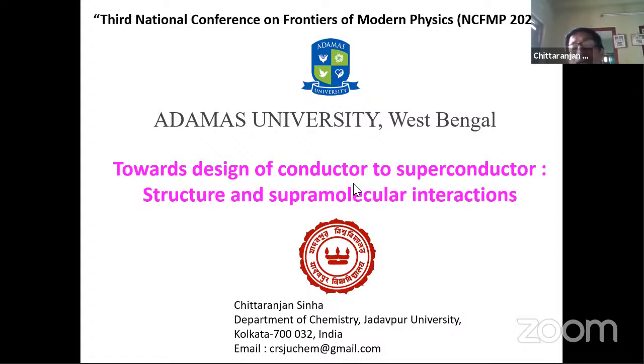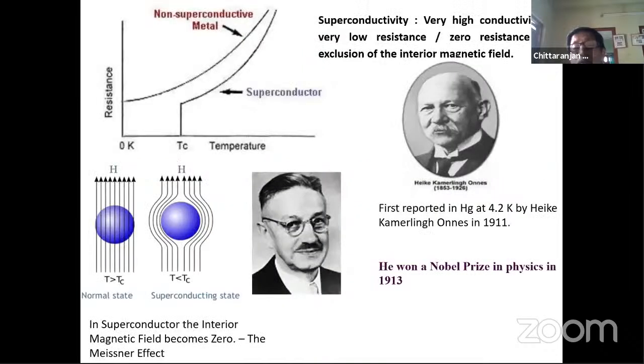If we go through the conductor, semiconductor, insulator, and superconductor, the idea of the superconductor was first mooted by Kamerlingh Onnes in 1911, where he showed that at a very low temperature like 4.2 Kelvin, even mercury shows superconductivity. This resistance versus temperature plot shows that the superconductor, after the critical temperature, shows superconductivity. In that superconducting phase, the interior magnetic field also comes to almost nil. So the magnetic property and the conductivity are interrelated.